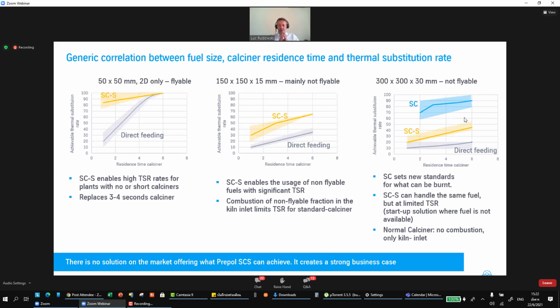You can understand here the unique advantage, creating a strong business case with an extremely rapid return on investment for the substitution rate. As you can see here, with 50 millimeter granulometry of the alternative fuel, let's say flyable, you can see the difference in substitution rate you can have when compared to direct feeding with a low residence time calciner of up to 4 seconds.